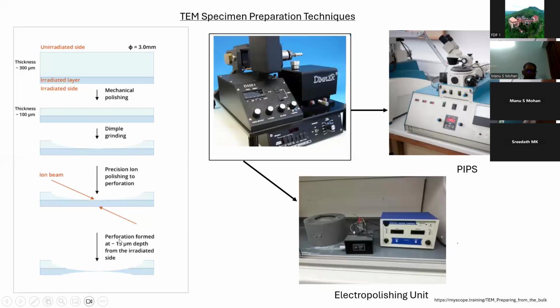So the hole in TEM is called vacuum. If you can afford more specimens and want a much larger area, you go for electropolishing. In this process, your sample acts as the anode in a typical electrochemical reaction, with a platinum electrode dipped in an electrolyte. When you apply a potential, the reaction happens, the anode gets oxidized, and you produce the hole, which acts as the electron transparent region.